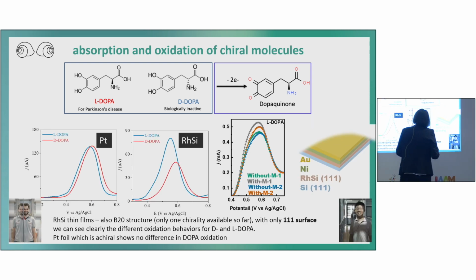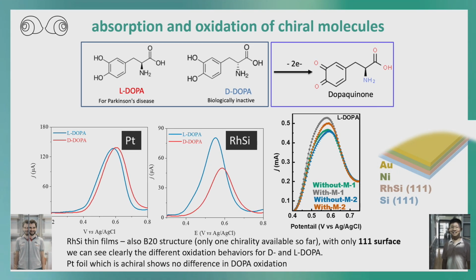And we also did this on thin films, because it's even more clear on thin films, since they have only one surface, not many facets. And we compared it with platinum. In platinum, you don't see anything. In the crystals, you see something. And the interesting thing is also, because we have this big magnet now for doing catalysis, we see that we can enhance the catalytic or redox reaction in the magnetic field. Anyway, these are all unpublished data so far, or they were partially submitted for some patents.